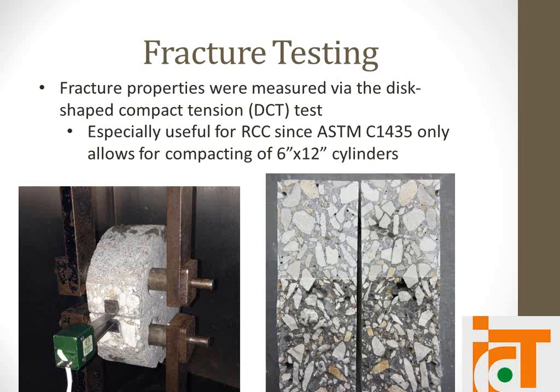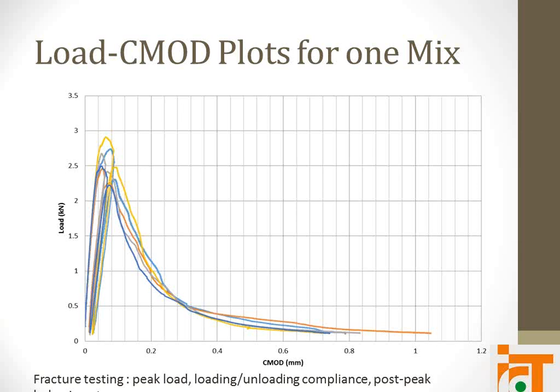We've also done some fracture testing, with Armin's help in teaching me. One of the benefits of using the DCT test as compared to the typical SENB test for concrete is that there's an ASTM spec for making 6x12s, which is what you would cut DCT specimens out of, so that works well. Otherwise, you'd have to make SENB beams, which has been done by Alex and Eric, and there's no spec for making those beams. To test using the DCT, we measure the load versus crack mouth opening and load it, and once it reaches its peak load, we unload it to get the unloading compliance and then reload it again until failure or around 0.1 kilonewtons.